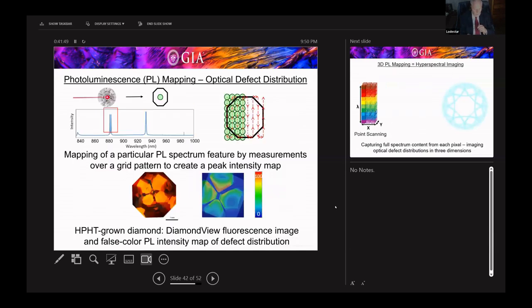We also have a way of doing a photoluminescence map. So I show you on the upper left just a PL spectrum, and I've got a couple of features at 880 nanometers circled. You can set this device to only look at that feature, and you can capture that feature in the diamond. And then you can move the location, as shown in the upper right, across the surface of the diamond. And you can create an intensity map